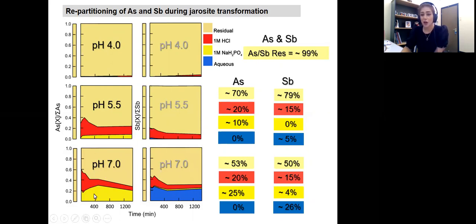But at pH 7, these two trace metals and metalloids behave very differently from each other. This time, the surface adsorption of arsenic was even higher. It was about 25% of arsenic, which actually moved to the surface of goethite, because jarosite wasn't jarosite anyway, it was goethite at this stage. So it was surface adsorbed to goethite, and the rest stayed inside the structure. But what happened with antimony was different, and it was released to the environment, to the aqueous phase. In less than 24 hours, about 26% of antimony was observed in the aqueous phase, and it stayed there over the course of the mineralogical transformation, regardless of the mineral that formed, either green rust, jarosite, or goethite.